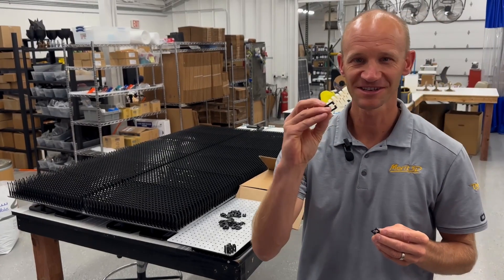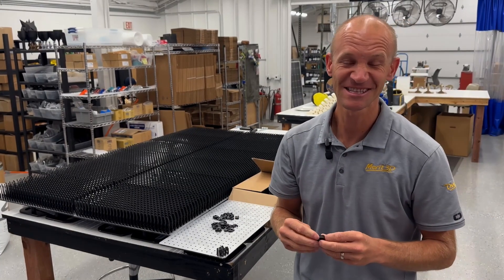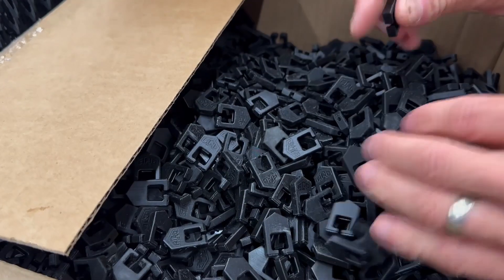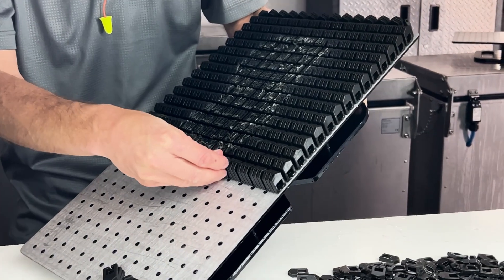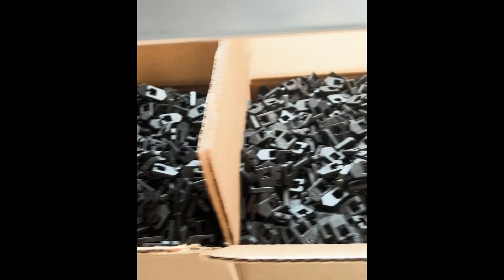This particular part is a binocular tether for Alaska Guide Creations. They sent us an order for 5,000 pieces, we printed it, they loved it, then they sent 25,000, then 60,000. We figured out that if the stars aligned we could print 60,000 of these in under a day. We started prints at 8 o'clock in the morning and delivered 62,700 of these parts at 4:30 in the afternoon — including post-processing. We could fit about 1,000 binocular tethers on one plate, and because the part is about three-quarters of an inch high, each print took about 45 minutes.